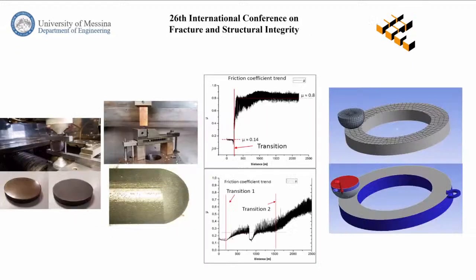So the first step of the work is the evaluation of the friction coefficient for the ceramic on ceramic coupling, and the friction coefficient is evaluated through the pin-on-disc tribological test. So basically, the first step is the specimen preparation. With the EDM technique, obviously both the disc and the pin are realized in this ceramic composite, with the electrical discharge machining, and through the tribometer it is possible to evaluate the friction coefficient.